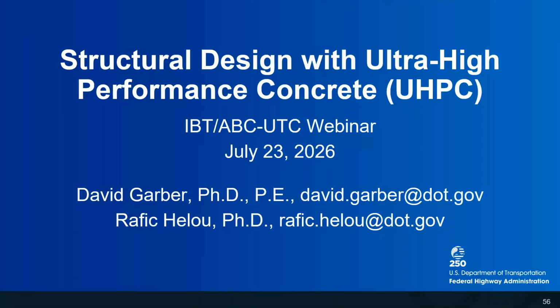Okay. When using UHPC for a closure pour between precast deck panels, what would the cure time be compared to maybe high early strength concrete? It really depends on the UHPC mix. You could see a mixture with no special curing, just ambient cure, where by using different superplasticizers, just like in conventional concrete, you can get an early strength. You would need probably 12 to 14 KSI to open the bridge to traffic in these situations. So you could probably get it in 14 hours to 16, 18 hours, but you will have to specifically request that, because the UHPC mixture is not unique. Just like in conventional concrete, you will have to get a mixture that is designed to have such an early strength within the short time that you probably need for a closure pour.